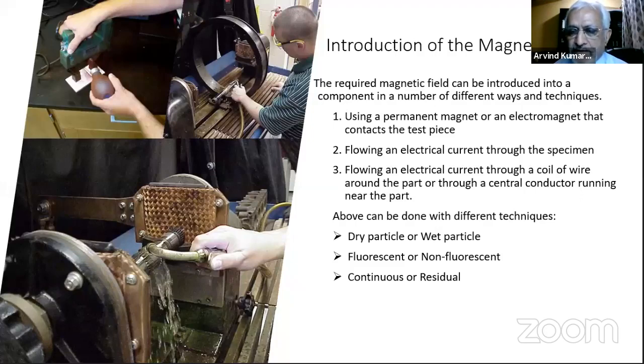You will have to demonstrate to me that yes, you are having a good amount of magnetic field. Because I have seen in practice, pipes at the bevel end, they do MPI to make sure there are no exposed laminations. When the pipes are produced in the mill, there is a standard practice that they do the MPI of the bevel end of the pipe by magnetizing the end and then carrying out the process. Now I've seen this process being done on plain carbon steel pipe, that is your standard pipe A106 grade B, and they are magnetizing the end, removing the field, and applying the wet particles and seeing there is nothing and everything is cleared.